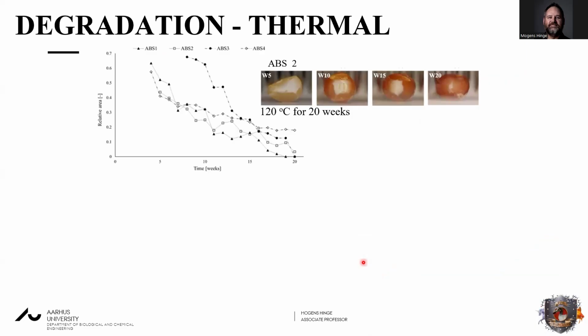Now, let's look into the thermal. And the thermal, I showed you this picture where we have the thermal material. So we have the white material. Remember that the material was white right in the start. And then after 5 weeks at 120 degrees, we start to see this yellowish or orange, brownish shell around it. After 10 weeks, we start to see even more and more. So by simply looking at the amount of white in each of these pixels, making it relative to the surface, then we can actually get our first indication that something is going on. So just looking at the color alone and seeing this ratio, we actually see that we have a very nice degradation as function of time here.